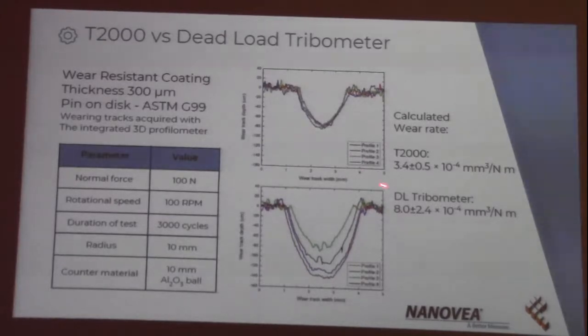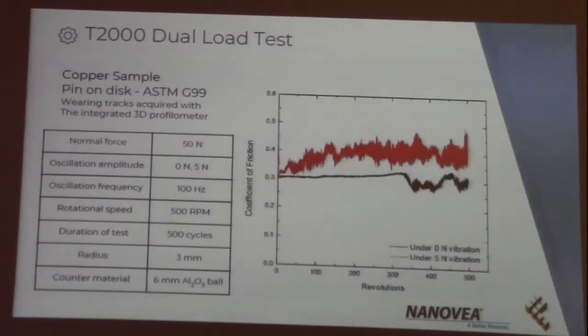that since there is no undesired vibration during the test, all the wearing tracks are of the same shape. Instead, with the standard dead load tribometer, where the vibrations are not taken care of, you have different behavior of the materials in different positions, and so you have a less accurate result on your test. Then we performed two tests with the dual load.